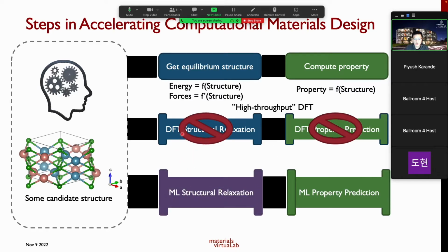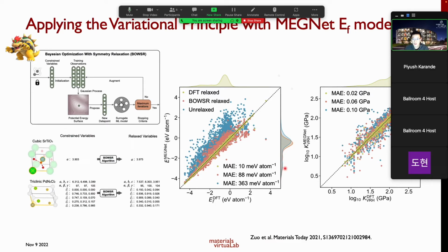So what we really need is to replace this DFT structure relaxation with machine learned structure relaxation, okay? So we actually explored a few ways to do this. The first way is just by applying the variational principle using our formation energy MEGNet model, and by using Bayesian optimization to relax the structure and finding the lowest energy structure, we can already do a relaxation of the crystal structure, right?